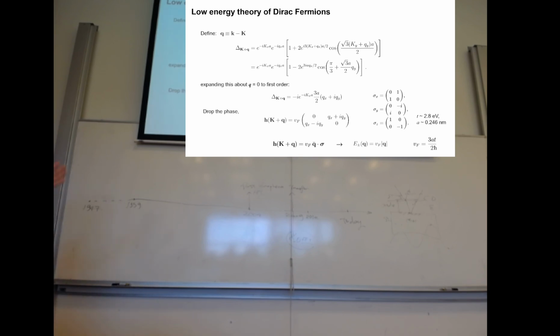So then we already have that band structure plotted in a 3D manner. It's very complicated. It has 6 cones. How do these cones look? We use the low energy approximation. That is just defining a new vector as k minus K, sitting at the K vector, taking a little delta away from there, and you have a new expression from here. After some calculation, you'll get the Hamiltonian like this one. So the Hamiltonian becomes Vf, the Fermi velocity, times the momentum dot sigma, which is the Pauli matrix. And then this prefactor Vf is defined simply by the atomic constant and this hopping parameter.